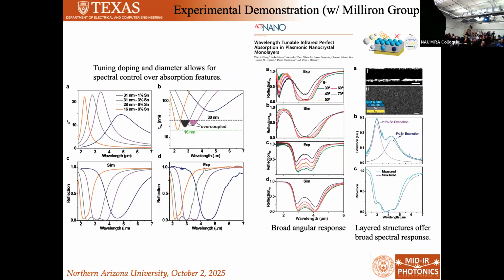We can control the width of our absorption by controlling the number of layers. We can go from undercoupled to overcoupled to critically coupled. We can tune across wavelength by controlling the thickness of the cavity, by controlling the doping of these nanocrystals, right? And so we can basically build these perfect absorbers across the mid-infrared.